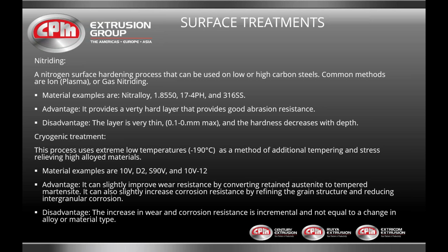Material examples are 10V, D2, S90V, and our 10V12. Cryogenic treatment can slightly improve wear resistance by converting retained austenite, and slightly increase corrosion resistance by refining the grain structure and reducing intergranular corrosion. The disadvantage is the increased wear and corrosion resistance is incremental and not equal to a change in alloy or material type. It adds cost too, so the additional benefit is usually not worth the extra cost.